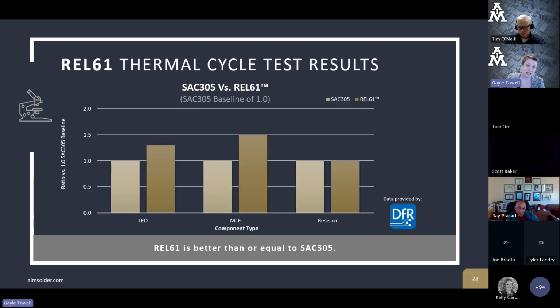We've done thermal cycle testing with this alloy. This is compared with SAC305. These are three different components we did measurements on. The line where SAC305 is, which is the lighter color, is our baseline, and this is how REL61 compared to SAC305 in performance. So it outperformed on the LED component, on the MLF component, and was similar on the resistor component. And this was third-party test data. These are the results they got. So thermal cycle testing, depending upon the component, was equal or better than SAC305.